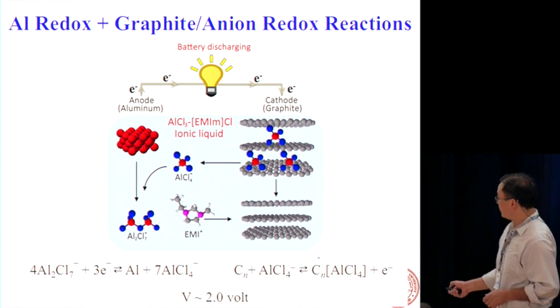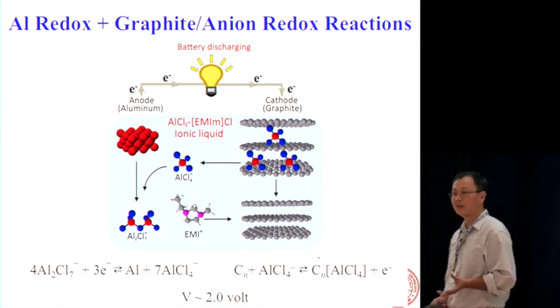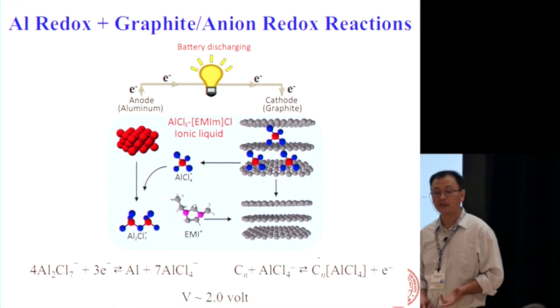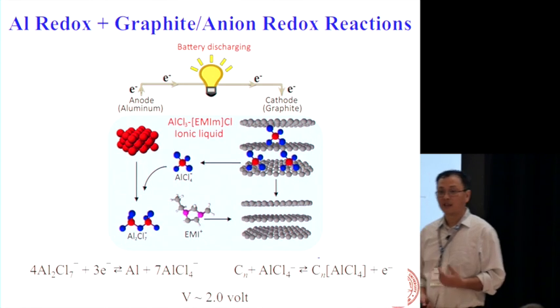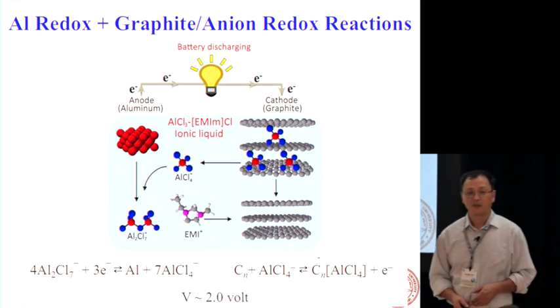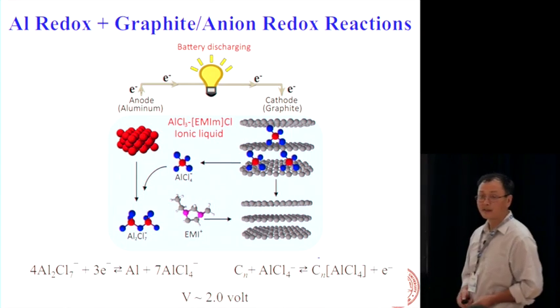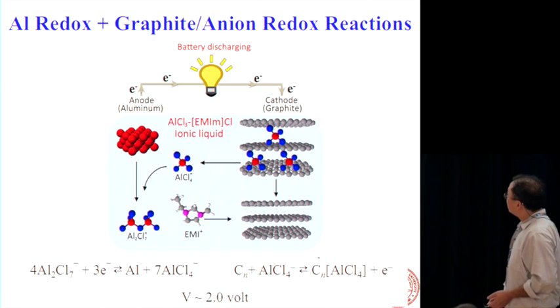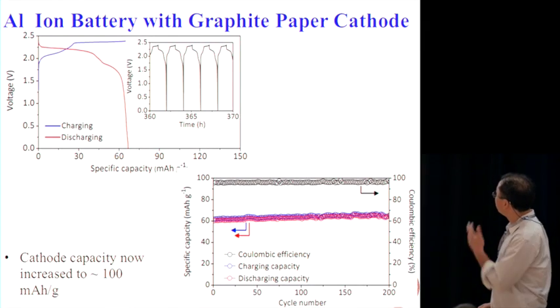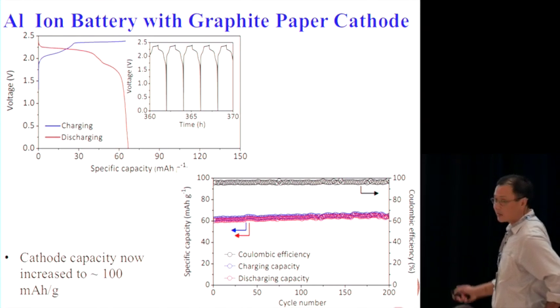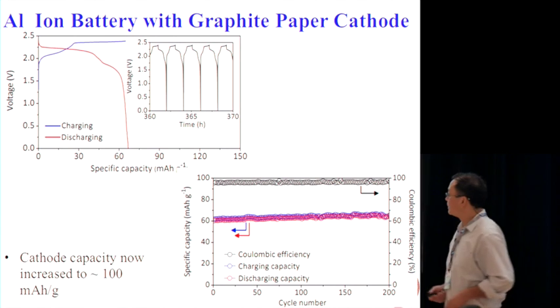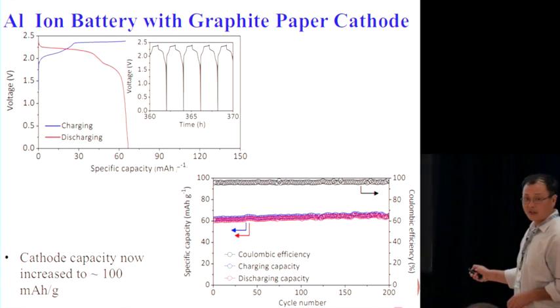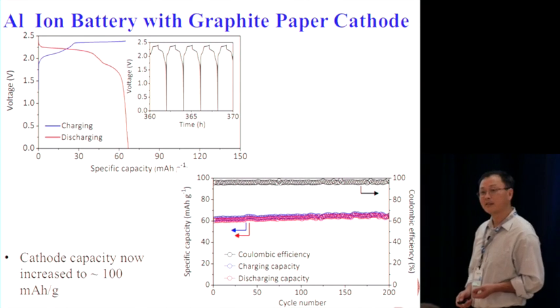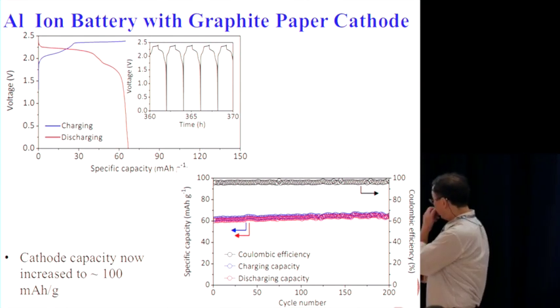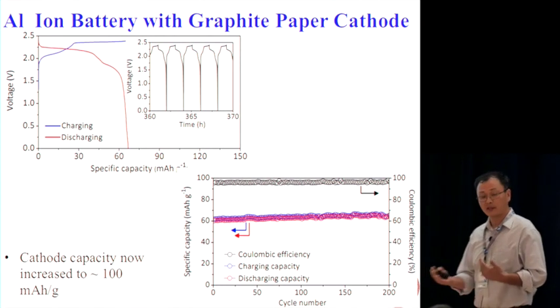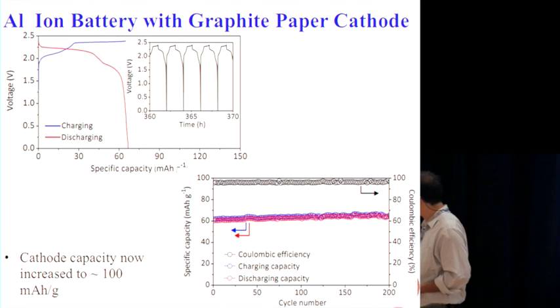And the voltage between these two redox couples is about 2 volts. Okay, it's not great. It's not as high as lithium-ion batteries, but it's 2 volts. Okay, it's enough to drive the water splitting we have in the lab. It's higher than alkaline battery. So that's the simple version of this battery, and you can see these charging and discharging curves to look at the intercalation process. The Coulombic efficiency is pretty good. We can get now to 99% okay? And cycle life is good. This is 200 cycles, but we have much higher cycle life data now.